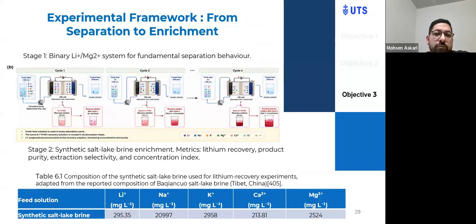For the experimental framework, in stage 1, we optimized the binary lithium to magnesium system with conventional batch CDI experiments. In stage 2, we used the synthetic salt-lake brine as presented in this table with the multi-enrichment process. It means in every cycle we used a new feed, but we used the same desorption solution to enrich the lithium in the desorption phase and collected the lithium, to understand how we can balance the selectivity and purity of the lithium.